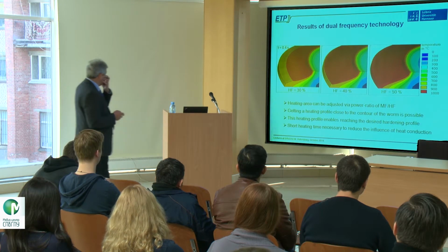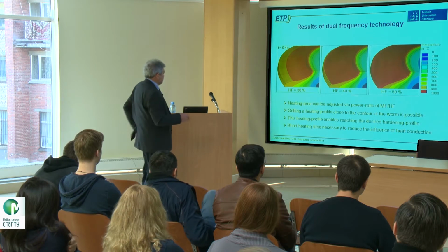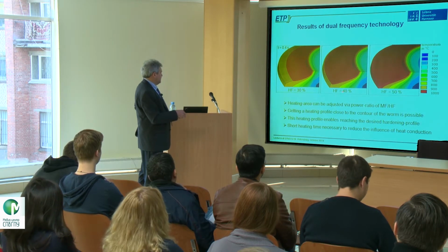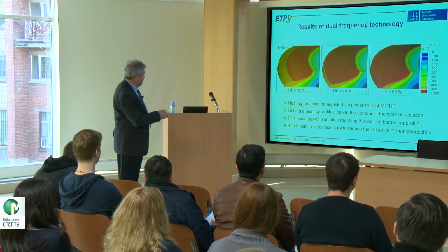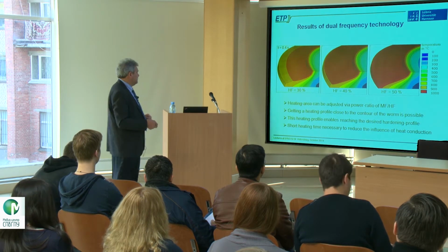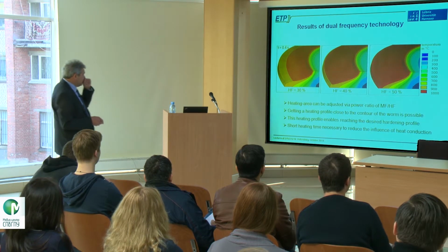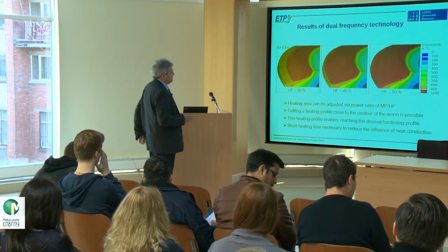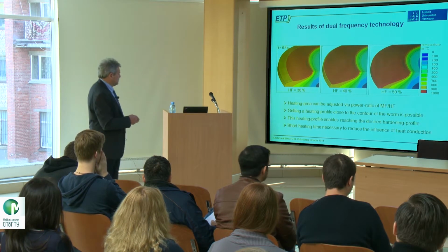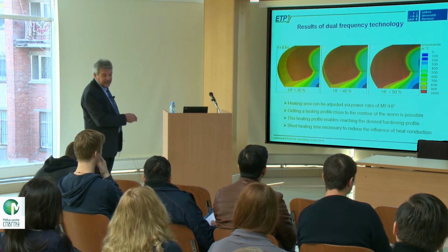And here you see the results now. The parameter here is the participation of high frequency. You see 30% high frequency, 70% medium. Here it is 40-60, 50-50. And after our simulation, we found out for this application that 50-50 gave the best results.